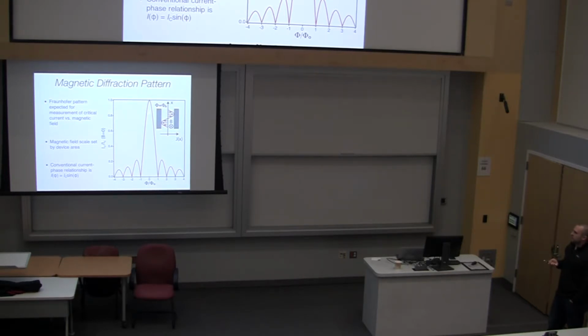One question would be, what is this critical current, or the point where the device goes from superconducting to normal? How does it depend on magnetic field? So you can think about, this is my superconductor, this is the other superconductor, this is a junction in between. I want to know what happens when I put a magnetic field into the board. Let's say I put one flux quantum of magnetic field in this region into the board. Then when I look at the phase evolution along this junction, I should get a 2 pi phase evolution from the Aharonov-Bohm effect along the width of this junction.